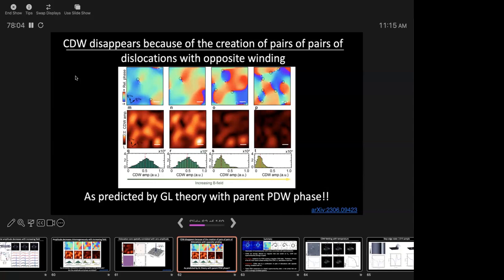Also, to see vortices, we would need to scan very large areas, and it's hard enough to see the superconducting gap as it is. If your tip picks up one impurity, then you can't see the gap anymore. It's very delicate; you have to be careful. The dislocations would be associated with the vortices in theory, but we can't see the vortices directly.